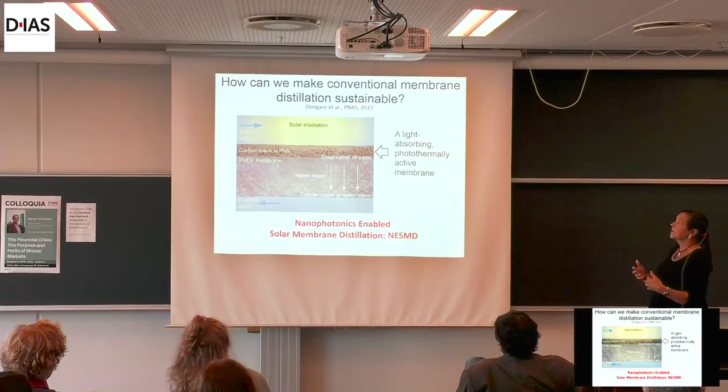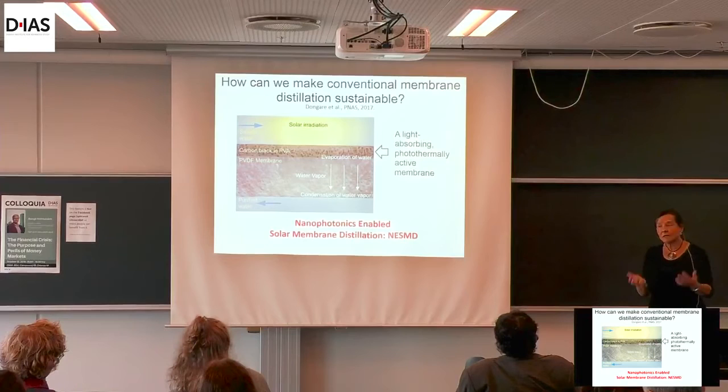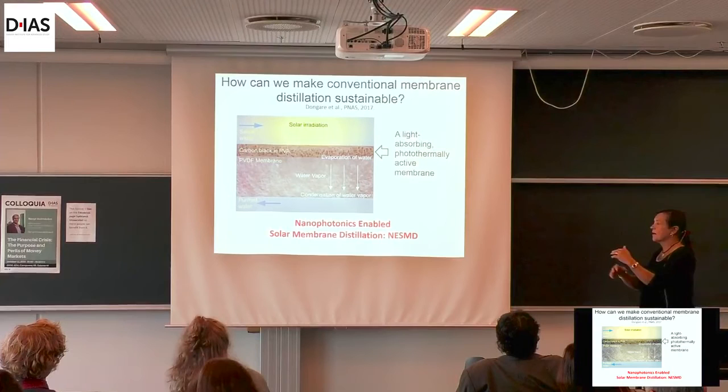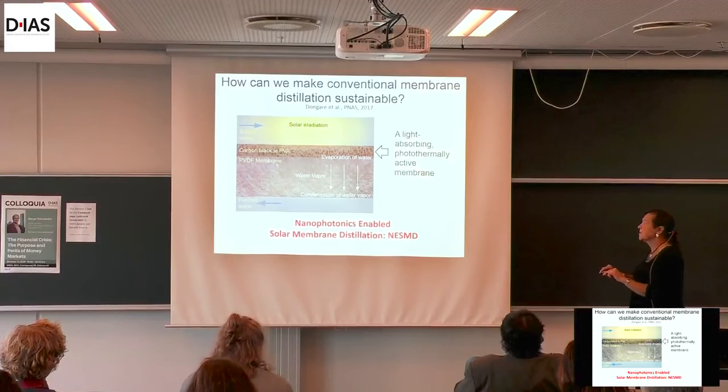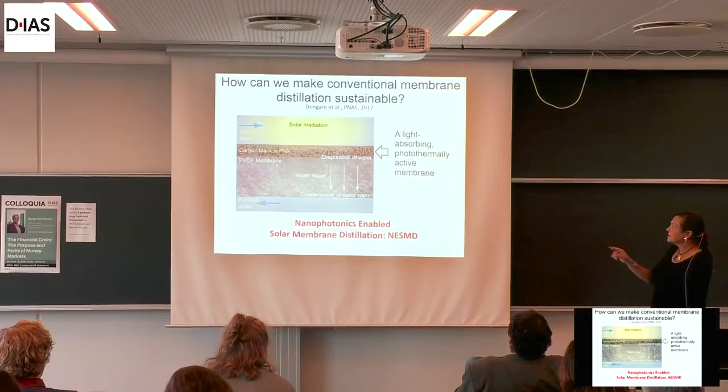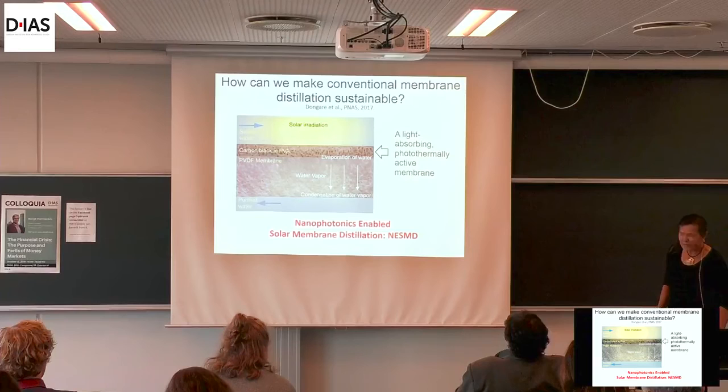And so now we don't have to heat the input water. We just flow the water, same temperature on either side of the membrane. We flow the water and it is locally heated at the input face of the membrane. And then the heated water becomes vaporized through the membrane and condenses on the other side. So we call this, couldn't think of a better acronym, NESMD, nanophotonics enabled solar membrane distillation.